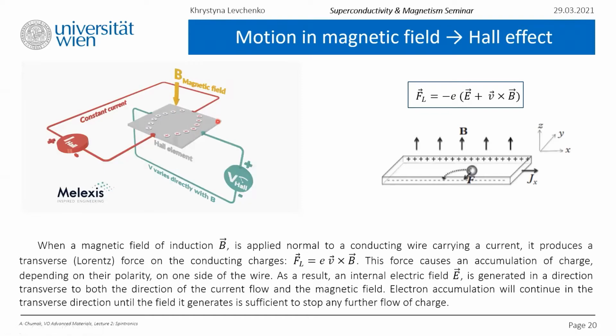This means that if we put a meter now between the sides of the plate, we will be able to measure the Hall voltage. The Lorentz force causes accumulation of charge depending on the polarity, and as a result, there is an electrical field generated in a direction perpendicular to both the current flow and the magnetic field. And the accumulation will continue until the field generated is sufficient to stop any further flow of charges. The general expression of the Lorentz force is given in the top equation here.